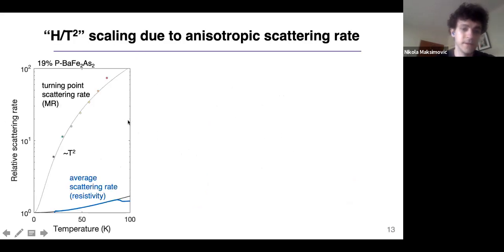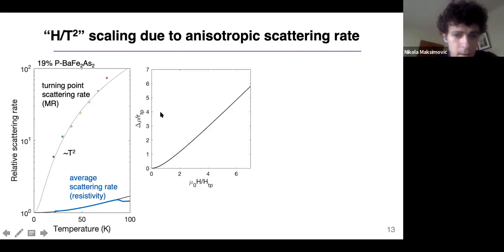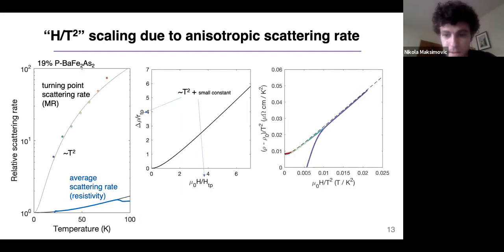One of the interesting things about this highly anisotropic scattering rate is that the magnetoresistance is primarily controlled by these two parameters, and we observe that the temperature dependence is much stronger than the zero temperature value. So effectively, both of these parameters go as T squared, like the scattering rate, plus a relatively small constant. This leads to a very simple scaling relation for the magnetoresistance, where you can divide the resistivity by temperature squared and the magnetic field by temperature squared. And we see that it fairly well captures the experimental data.